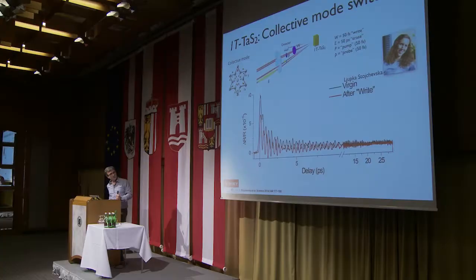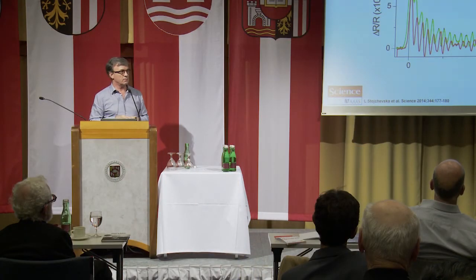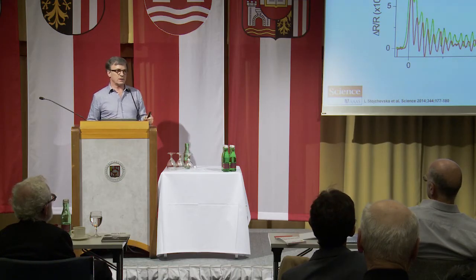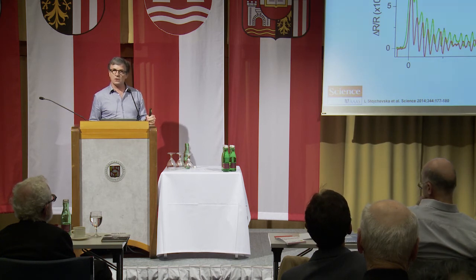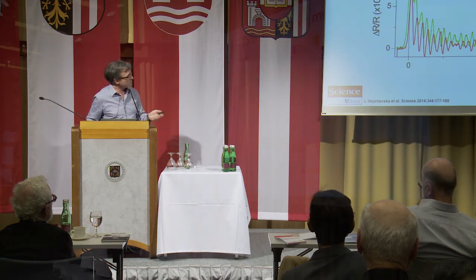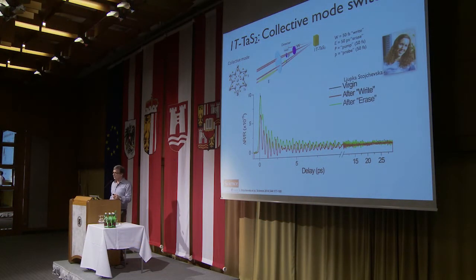No, actually, it turns out we haven't, because if we just carefully heat the material with another laser pulse, we recover exactly the original spectrum. You see, the green and the black are right on top of each other, almost identical. So basically, we have a reversible change in the material, in the optical response. Great, fine. This could be anything. Well, the obvious thing at the time was, maybe we're inducing a new state, this red thing, and maybe it's superconducting. Photo-induced superconductivity has been another common interest, I think, with Alan.